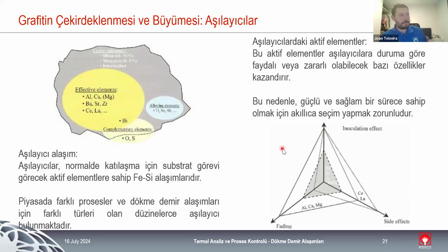And this is basically what inoculant is. It is a ferrosilicon alloy with some active element, with some barium, aluminium, calcium, manganese, zirconium. As with everything in life and everything in cast iron production, some elements have good effects. After some time, they lose the effects. They have a quick fading time, like bismuth and lanthanum. They are really good for late stage inoculation, but they are not so good for early stages, for ladle inoculation. We have the universal inoculant with barium, with zirconium.